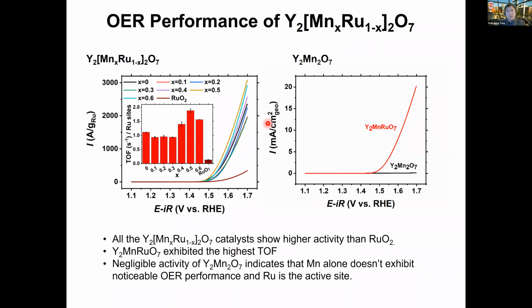Just to make sure the performance is coming from the active site, ruthenium, we also checked the manganese site by itself. If you purely use the yttrium manganese oxide, there is little activity that can be measured. That suggested to us that ruthenium is still the active site, but by introducing the manganese, we can effectively tune the ruthenium's reactivity in the OER reaction system. So this site tuning becomes quite interesting.